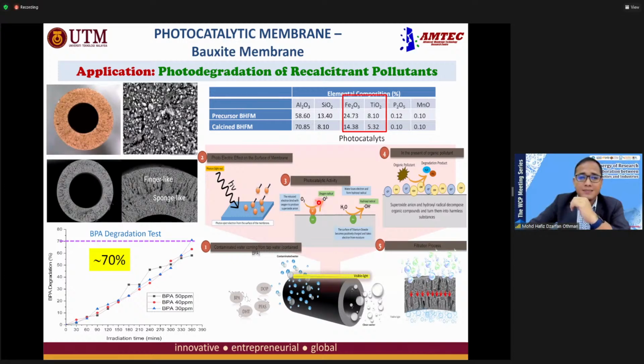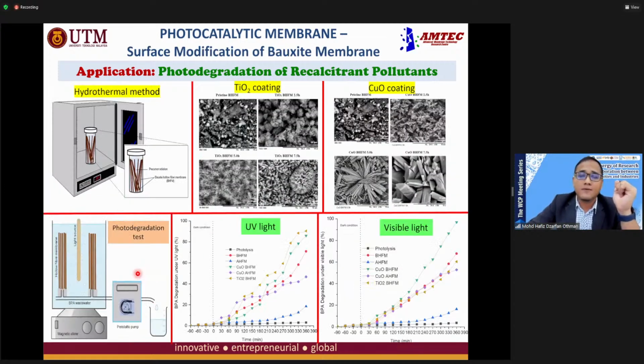We tested with some recalcitrant pollutants like bisphenol A, and by using this membrane, we were able to reject 70%. But this is actually not good enough. We tried some modifications using a hydrothermal method in order to add more photocatalyst on the membrane. So we coated it with titanium dioxide and also copper oxide. Titanium dioxide is used for UV light radiation, and copper oxide is used for visible light radiation.